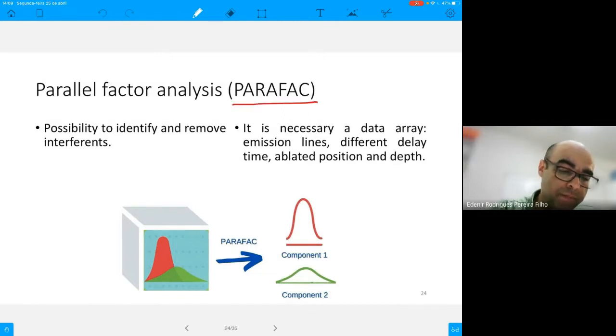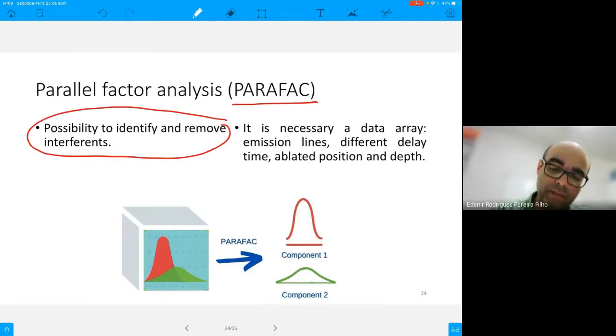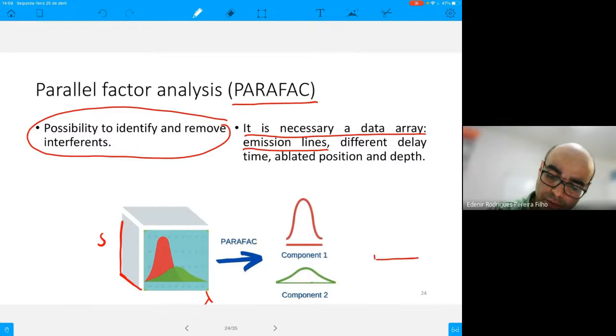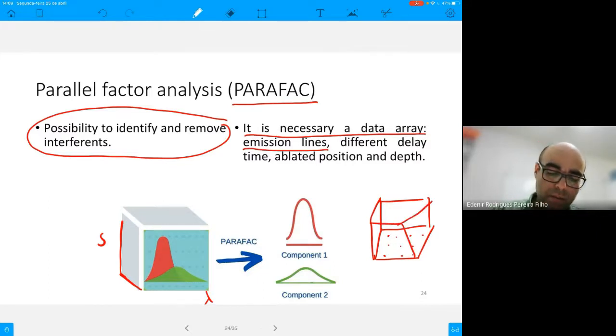Parallel factor analysis, PARAFAC. In PARAFAC, we also mathematically remove interference. It's necessary to have a data array. We can prepare this data array using emission lines in one mode, emission lines, different delay times, for example, and we have a signal. Or we can have different positions of the sample, and you have here the array for this type of data. And we can identify interference and remove this interference in the sample.